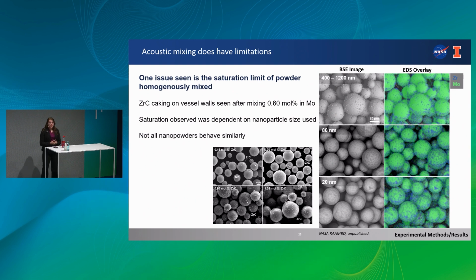As you'd expect, the saturation limit depended on the nanoparticle size we used. We used 3 different sizes of zirconium carbide, and we were able to get a lot more coverage of the molybdenum powder with the zirconium carbide as we decreased the nanoparticle size, as you can see in this EDS image. But one thing to note is that not all nanopowders behave similarly. We tried this with tantalum carbide, and the tantalum carbide was a lot more agglomerated and stuck together, so we didn't get a nice uniform distribution, and we're still trying to figure out the best way to approach adding these different nanoparticles. Do we need to mix for longer, or do we need to pre-sieve the tantalum carbide powder to make sure it has a smaller size distribution so it actually attaches to our molybdenum powder?